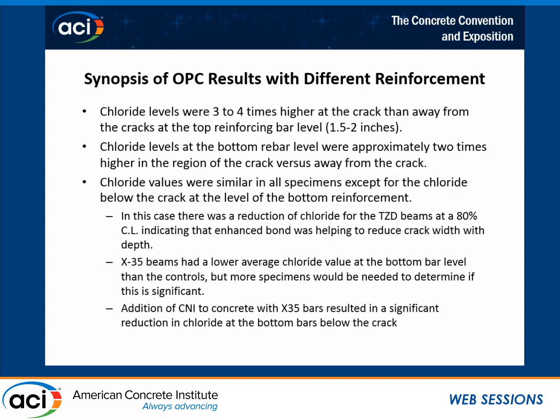Now, the synopsis of the differential material here is that chloride levels were 3 to 4 times higher at the crack than away from the cracks at the top reinforcing bar level, and that's 1.5 to 2 inches where that bar was located from the surface.